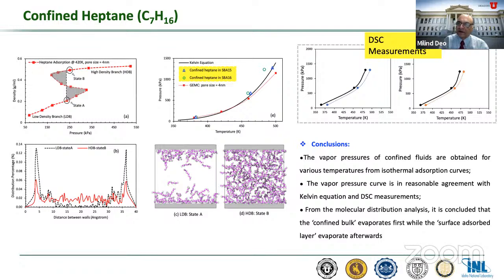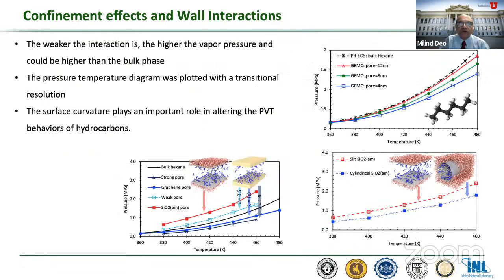So if a higher melting point means suppressed bubble point, that somewhat confirms the hypothesis that maybe the transition to vapor phase in shales is delayed because of the pore size. We are still looking more into this. With the Monte Carlo simulations, if you change the lambda factor, if you make it weaker, for example, it shows that you can modulate when the transition actually occurs, and sometimes it can even happen before or after. So it depends on whether you're dealing with graphite or silica in this case.